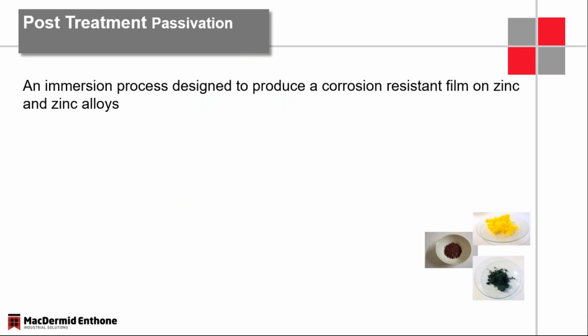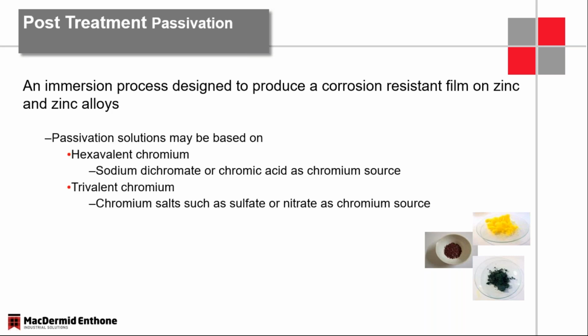So what are we talking about here, right? We're talking about an immersion process. We're talking about a conversion coating. We're talking about whether it's zinc alloy, converting the very, very thin area between the deposit and the environment that it is in. That trivalent acidic environment, and we are converting that zinc or zinc alloy to a zinc chrome complexed gelatinous water-based film.